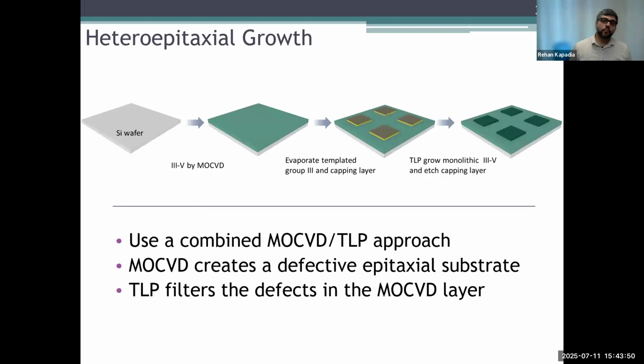So what we did is we said, all right, we have MOCVDs too, so let's use that. We took silicon and, in a naive way, meaning not thinking about defect filtering in any way, just grew a layer of indium phosphide on top of that. And then we said, let's do homoepitaxial growth of indium phosphide, of TLP indium phosphide, templated liquid phase growth, this liquid phase approach. Let's do homoepitaxy of that indium phosphide on top of our defective MOCVD-based indium phosphide. And so this is the way that we would do it.